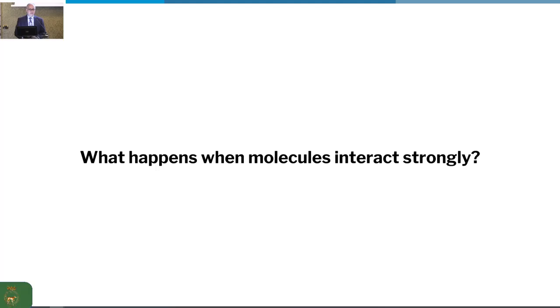So the question that we wanted to ask to do better and do more is what happens when molecules interact strongly? Instead of a bipyridine, or instead of neutral linkers that interact with metal ions, that bond is worth about less than 100 kilojoules per mole. But if I could put a charged linker instead of a neutral linker with transition metal ions, such as carboxylates, then that bonding interaction is much stronger because now you have a charge-to-charge interaction. And so that bonding interaction would be 3 times as strong as the traditional networks.